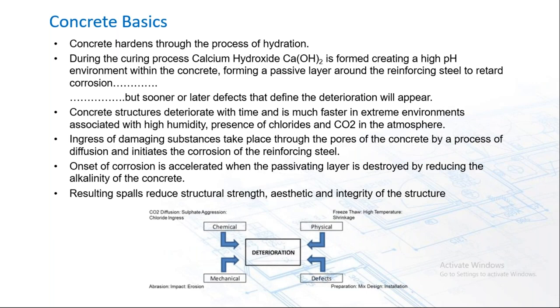So concrete hardens through the process of hydration, and during the curing process, calcium hydroxide is formed, creating a very high pH condition within the concrete. It forms a passive layer around the reinforcing steel that retards corrosion. But sooner or later, defects that define deterioration will start to appear. Concrete structures deteriorate with time and much faster in extreme environments associated with high humidity, presence of chlorides, CO2 in the atmosphere, wet and dry cycling.